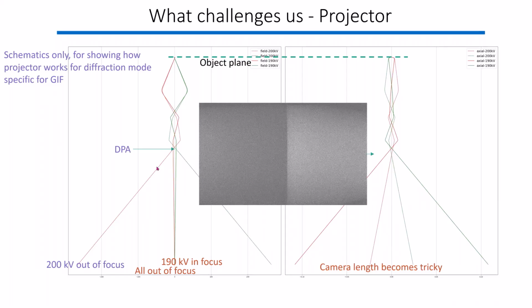So now if you start to align it, and if you want to make some theoretical prediction of how much you can do, you can make a simple simulation to see where the electron energy for 190 kV is in focus. And of course, the camera length becomes a bit tricky now, because if you're doing the scaling properly, the order of the camera length is somewhere between 200 kV and 190 kV. So that's one thing to remember.